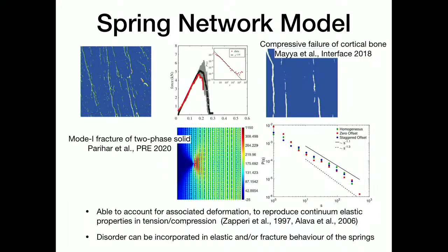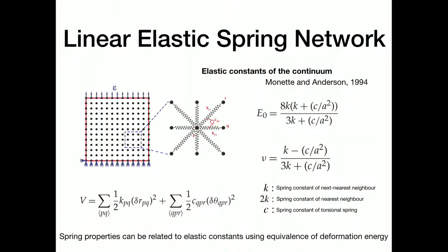So we use the random spring network model. We have utilized it initially for reproducing experimental data on bone, in which we find the compressive exponent to be roughly around 2. We are able to reproduce fairly well the experimentally observed failure planes. Then we have also done it for patterned two-phase materials and looked at the exponents there, but those studies are just background that we have used them.